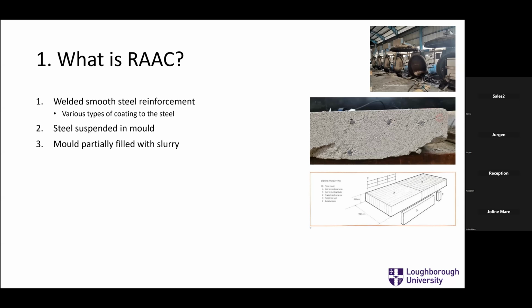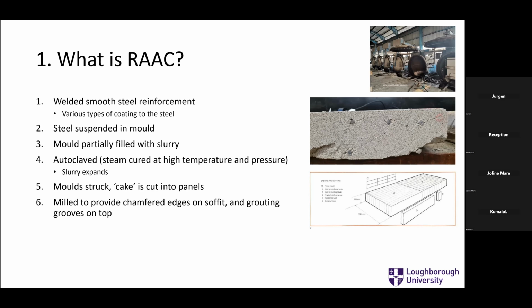So when it's made, the steel is dropped into a liquid slurry, a coating. There's a variety of coatings. Could be a cementitious, so a very higher strength, more concentrated cementitious sand cement slurry. Some of them are polymer modified. Nowadays, they're powder coating, so electrostatic coating to the reinforcement. They're put in the mold. You pour this slurry in. You put it in the oven. You autoclave it at high temperature and pressure, and the slurry expands due to the aerated nature.